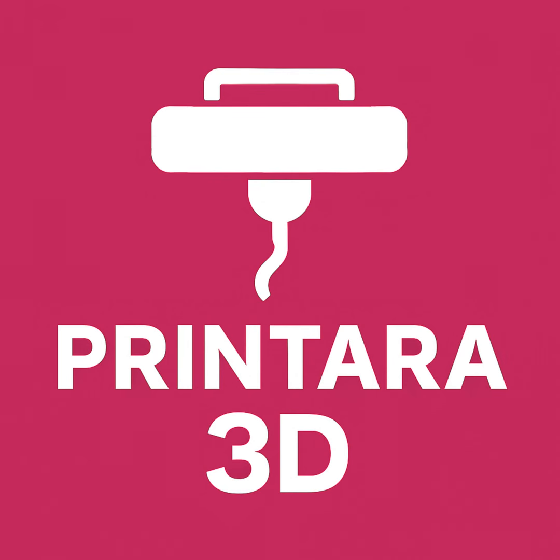Because ABS is soluble in acetone, you can perform a technique called chemical vapor smoothing. You take your finished ABS print and you place it inside a sealed, controlled container. Like a glass jar or a sealed metal bucket. Yes, and you introduce acetone into that environment. Usually you just do this by attaching paper towels soaked in acetone to the inside of the lid. Acetone evaporates very quickly at room temperature, and the vapors are heavier than air. So these invisible chemical vapors roll down and completely envelop your 3D printed part in a vapor bath.